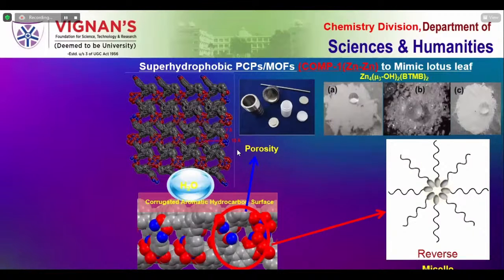Looking into the structure, the conclusion we can give is that this is the ligand and these are the metal centers. They are arranged in such a way that it is close to a reverse micelle structure. Reverse micelle means the polar groups are inside and the lengthy alkyl chains, the hydrophobic chains, are outside. So whenever you put a water drop on this kind of reverse micelle, the water drop will stay on top. Because of the hydrocarbon moieties, the water drop will not go inside. Our compound also has a similar kind of structure.